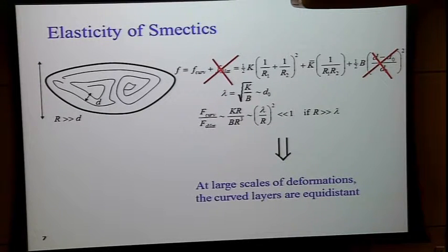So you are trying to create the filling of this droplet with the smectic layers, and the naive approach would be probably just to start growing layers from the boundary inwards. But since the space for these layers is constantly decreasing, you have to introduce a lot of dislocations that would account for interrupted layers.